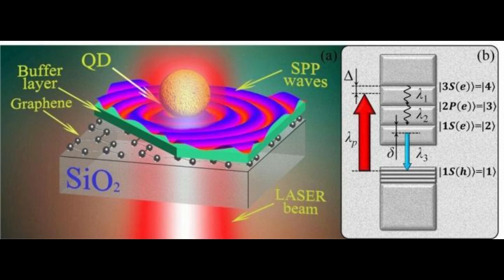The idea to use a quantum dot as a scatterer is not new. Some of the previous graphene studies used a similar arrangement, with the dots positioned above the 2D sheet and interacting both with light and with surface electromagnetic waves at a common wavelength shared by the two processes. This was made possible by choosing a quantum dot size that was exactly right. While such a system is fairly easy to tune to a resonance, it is susceptible to luminescence quenching, the conversion of incident light energy into heat, as well as reverse light scattering. As a result, the efficiency of SPP generation did not exceed 10%.